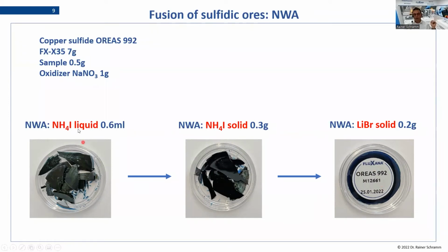Why? The iodide as a non-wetting agent is very volatile, so you lose a lot during the fusion. You lose more when it's liquid than when it's solid, and of course bromide is not as volatile, so in this case it remains better in the bead, in the melt, and this is why this gives the glass, while this still needs more non-wetting agent or a different flux, so it needs more optimization. So you see the way where you can go to optimize your recipe in a way that in the end you get what you want. So this is the real application development work.